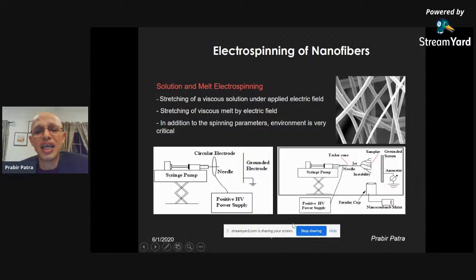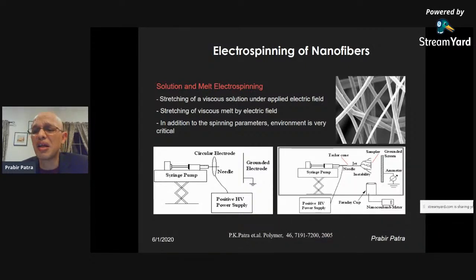Here I'm going to show you simple figures where we have shown that when you collect these small fibers like collagen, they're artificial and very small in size. You can change the size of these by various designs of electric field. If you look at the left side, it has a needle, and the needle is passing through a ring, and the ring is attached to a power supply. Here the needle is not directly being charged, but it is induced. So it's called inductive charging. On the other hand, on the right side, the needle is directly in touch with the charge. So by various charging schemes, you can make small fibers, intermediate size fibers, and larger fibers within the scale of 10 through 500 nanometers.